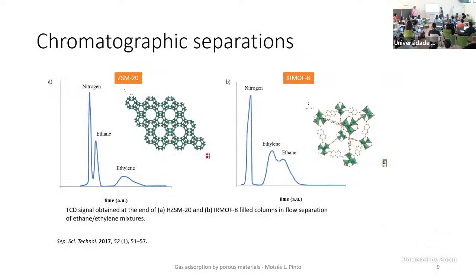Just to summarize, to conclude this first part, we can also use the materials in some type of separations in columns, like chromatographic separations. In this case, this was done at the lab, but it can be done at the industrial scale with big columns. In this case, this is a zeolite, and you see, when we inject, this is time, and this is the signal we have at the detector. So the mixture passes through the column, and then you have first nitrogen that comes out, then ethane, and then ethylene. So you are injecting them at the same time, but they come out at different times.